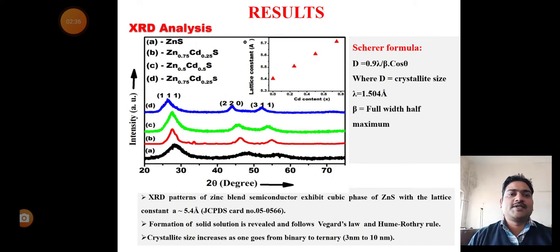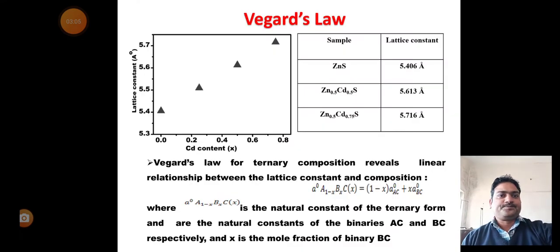The XRD pattern of the zinc blende semiconductor exhibits the cubic phase of zinc sulfide, according to JCPDS card number 05-0566. Formation of solid solution is revealed and follows Vegard's law and the Hume-Rothery rule. Crystallite size increases as one goes from binary to ternary. The particle size has been obtained as 3 nanometer to 10 nanometer.